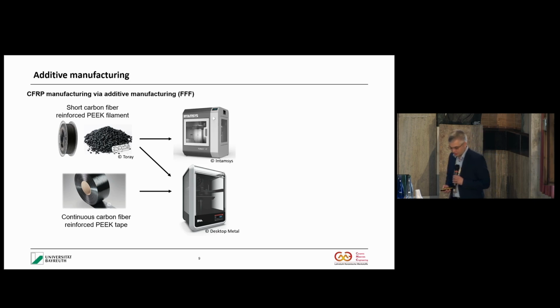In the project, we used commercially available filaments, which are optimized for the processing of CFRP. So they're not optimized for the processing of ceramic matrix composites, which means you have to work on the filaments a lot. These are short carbon fiber reinforced filaments, but there are also tapes available with continuous fibers. The big advantage is that it's a quite rapid technology. It's also an established technology in the last 15 years in the field of CFRP production.